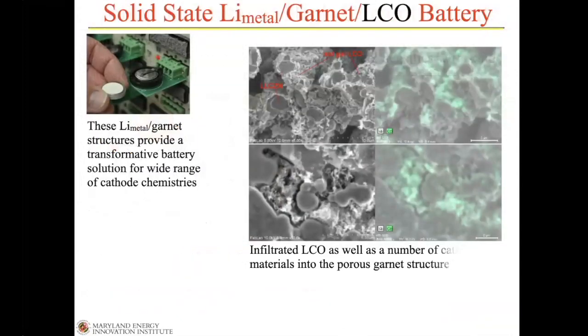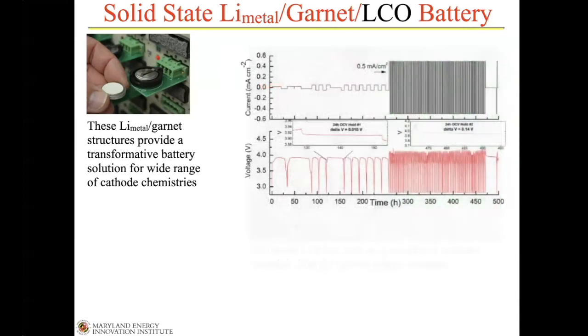So this now is a platform for all kinds of cell chemistries. We have lithium metal in the anode, we have a garnet structure, and now we're trying different cathode chemistries to show the performance. Here you can see some of our earlier cells using LCO as a cathode material. You can see the cobalt inside of the garnet pores. Here's the corresponding cycling data. The data above is the current density, the data below is the corresponding voltage. And this went on for well over 450 hours of cycling without any problem.